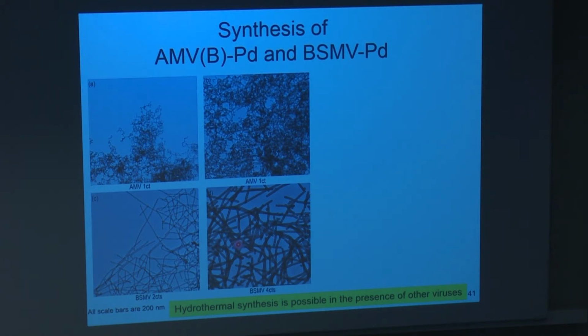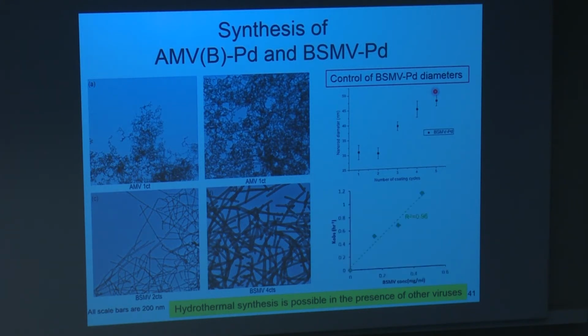So now we need to understand better what's going on with BSMV, but like TMV, it looks like the first and second coating, perhaps we didn't completely coat the BSMV with a layer of particles with the first coat. And so when we went up to third and higher coatings, you see the size of the coating actually increase with the number of coating cycles. And also, as I said before, the first order reduction rate constant actually increases as a function of the concentration of BSMV. And that's why we actually divided the rate constant by the mass of the